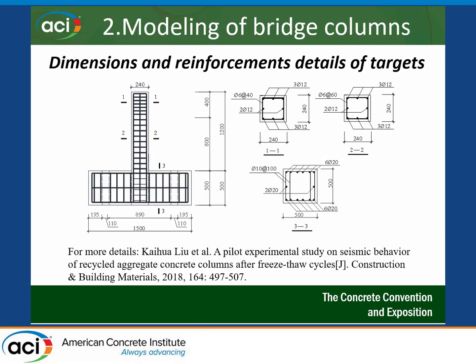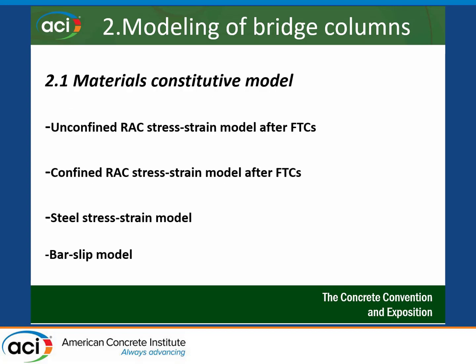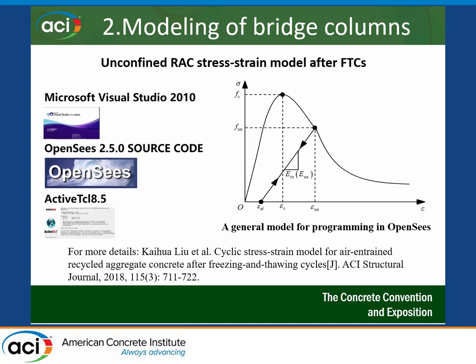Several specimens were tested under freeze-thaw cycles through a pilot experimental program to study the behavior of concrete columns. Based on the experimental results, constitutive models for the columns were developed. The unconfined and confined recycled aggregate concrete stress-strain models after freeze-thaw cycles were developed, along with a steel stress-strain model and a bar slip model, and these were incorporated into the OpenSees framework.